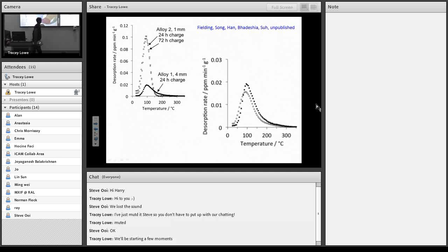Okay, so here are some calibration experiments first. We do not want to saturate the samples before measuring the TDA. Because if you saturate, then you've filled everything with hydrogen, austenite, ferrite, and the barrier effect becomes less significant. So we chose a sample thickness of 4 millimeters, compared with 1 millimeter, where we wouldn't saturate the whole sample, and the hydrogen can still move about without reaching solubility limits. If it had been 1 millimeter, we would have had a lot more hydrogen inside the sample during charging. And this experiment is simply to show the reproducibility. Okay, so two independent samples with the same heat treatment condition, same retained austenite content, you will get differences, okay, for whatever reason.